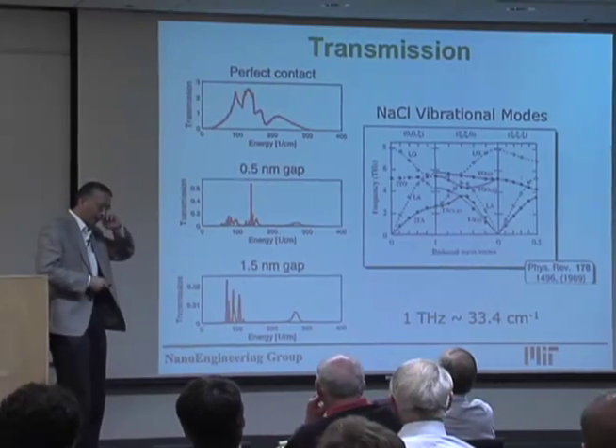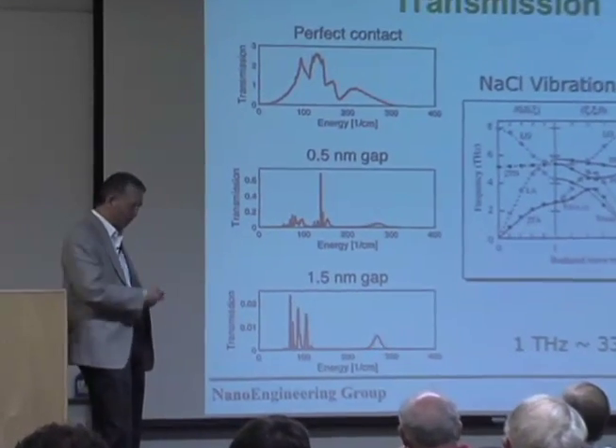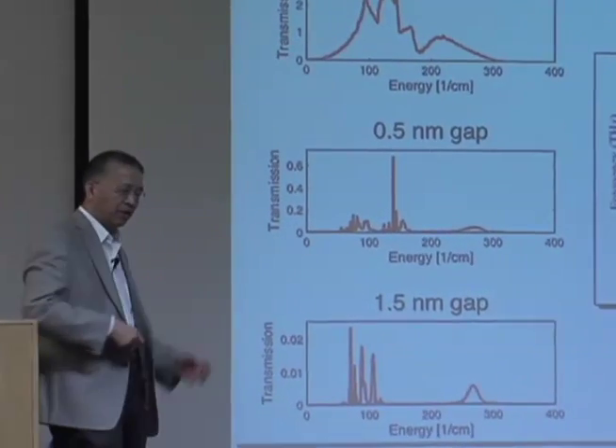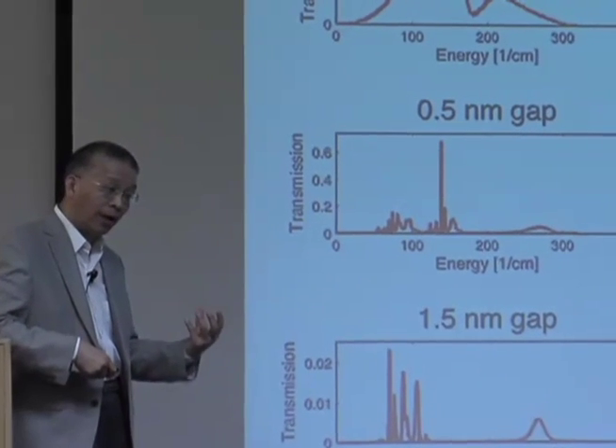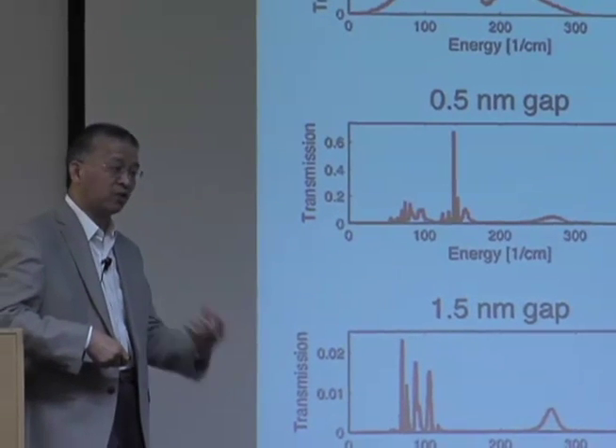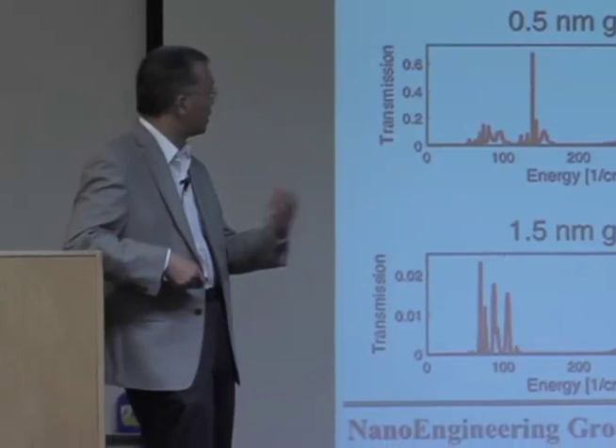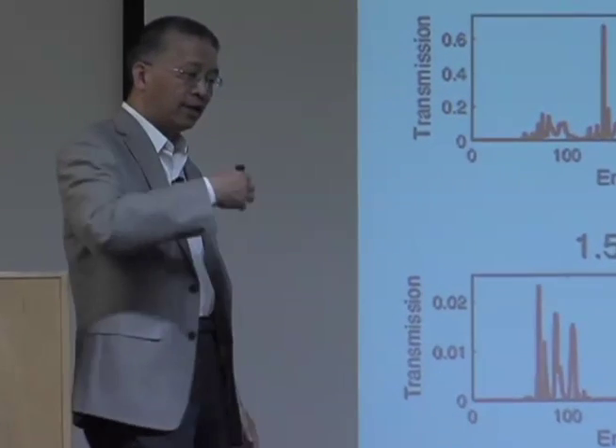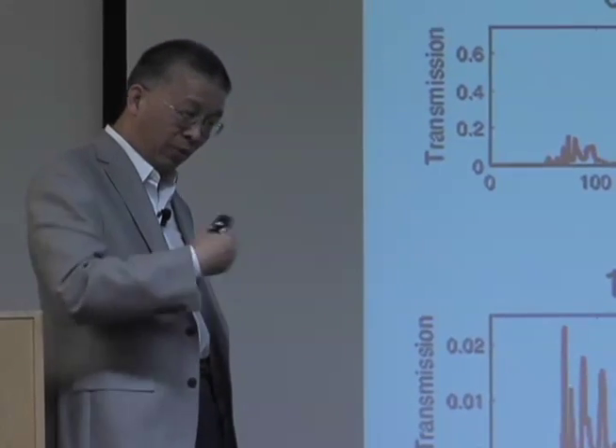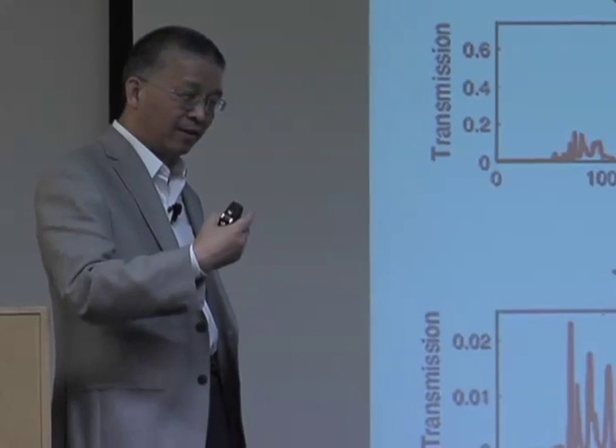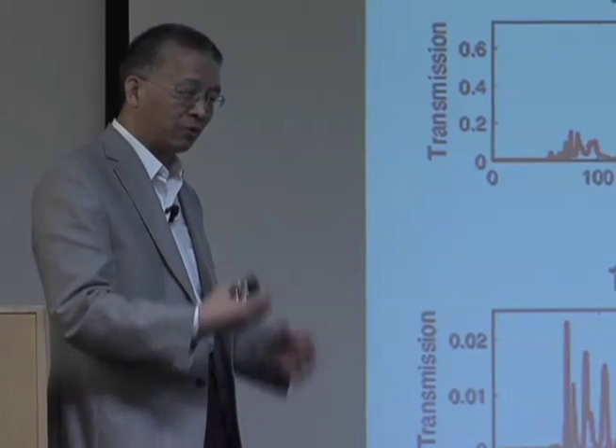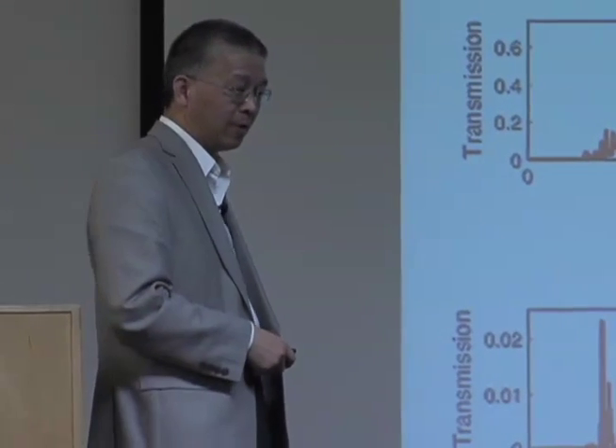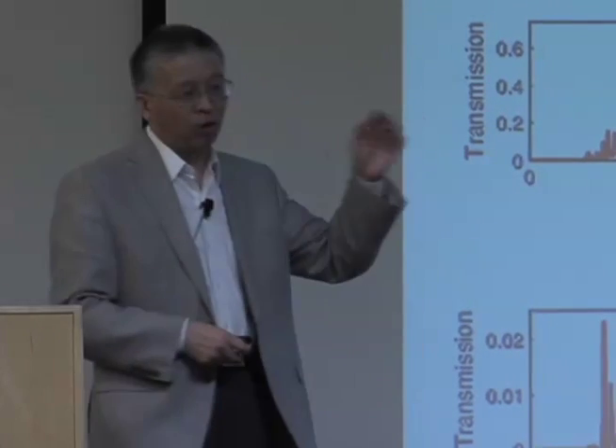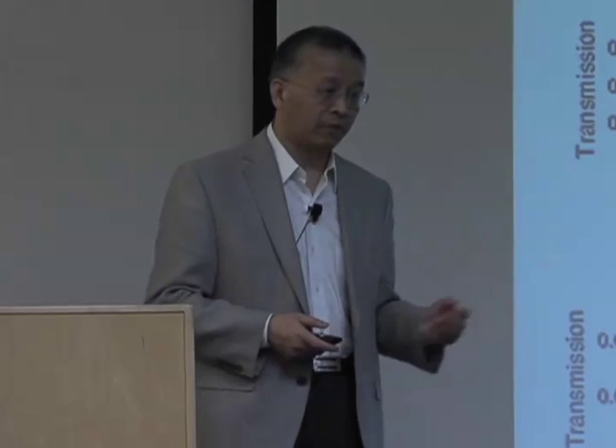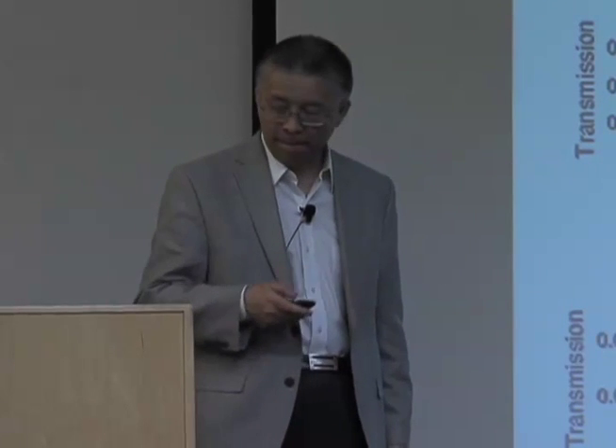This is not normalized. So here is actually density of states. So it's not normalized to the density of states. It's per channel. So if you look at these, there are three polarizations: one longitudinal wave, two transverse waves. That's why you can see the maximum there is 3. So we also have normalized data. You normalize to density of states, you'll get the absolute transmittance.